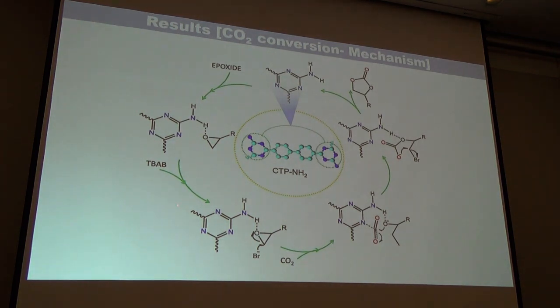And then we have also proposed a mechanism using the CTP1 material. We can see initially the epoxide interacts with the amine sites of the polymer through hydrogen bonding interaction. When we use the tetrabutyl ammonium bromide, nothing but the TBAB, this can open the ring of the epoxide because there is a bromine anion that can open this epoxide by attacking this beta carbon. So subsequently, this kind of intermediate will form.